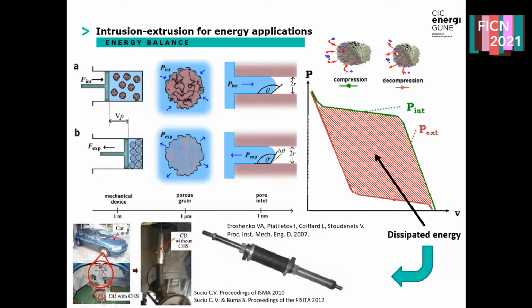And the fact that the work accumulated during the intrusion process is much larger than the work released during the extrusion process allows to dissipate mechanical energy, for example, energy of vibrations, like in this example, but also the heat which is absorbed by the system during the intrusion is typically much larger than the heat released during the extrusion, which helps to maintain those devices without overheating.